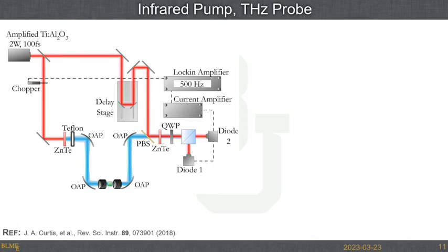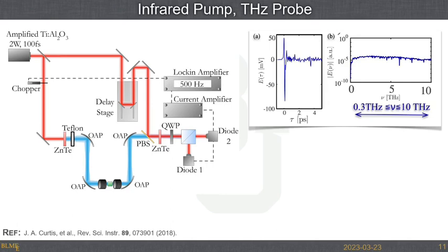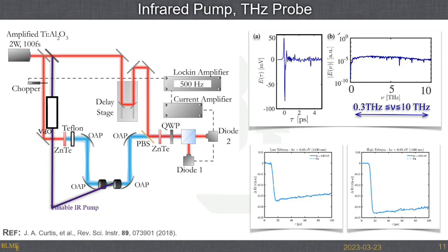And then the change that I'm going to make in the experiment that I'm going to talk to you about is to take a piece of all of this, that should actually be in there, something called an optical parametric amplifier, tune the wavelength out of this, and so I'm going to photoexcite the sample, change the conductivity of the material, and then study the changes to that using these infrared terahertz pulses. The geometry is called pump probe. And what you're going to see here, this is one of the signals, so I'm tracking the electric field here.